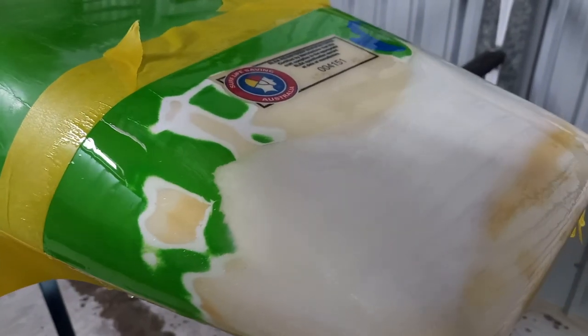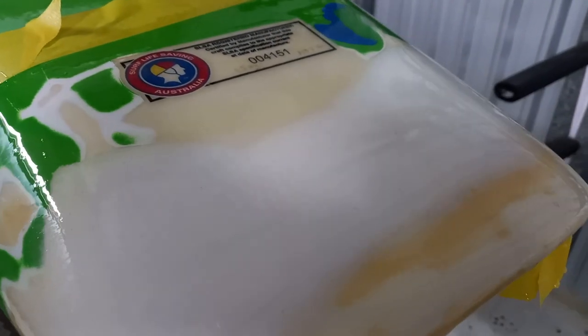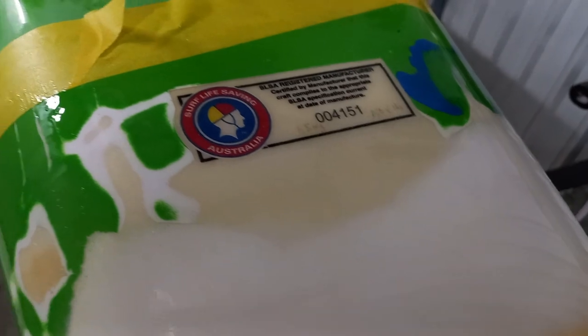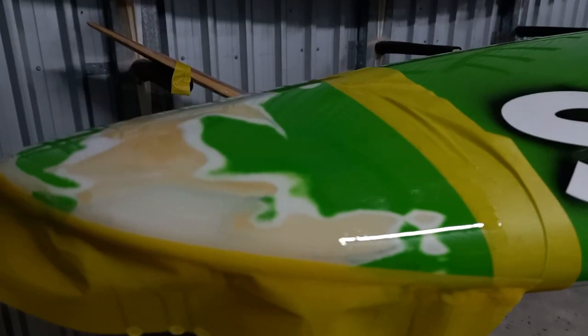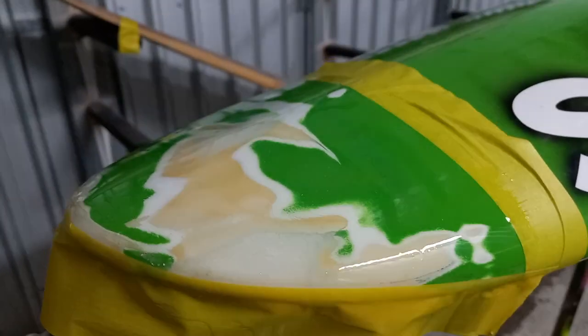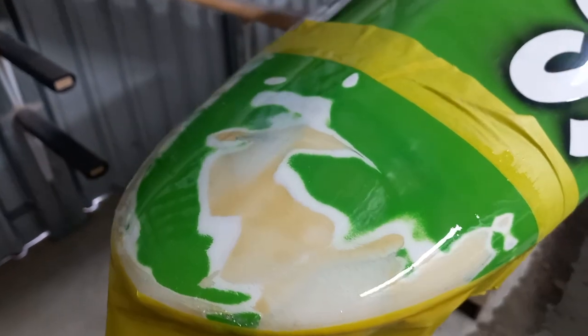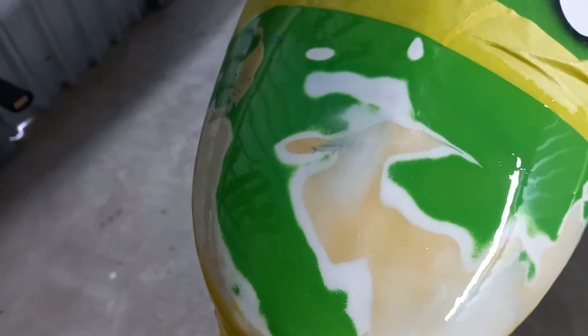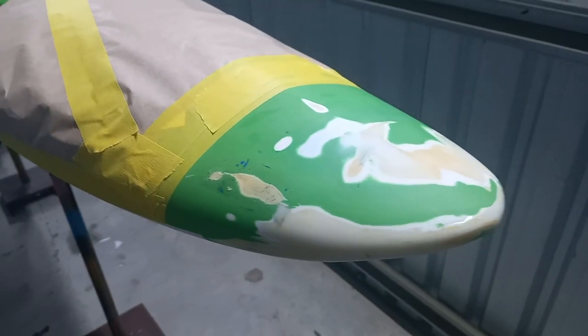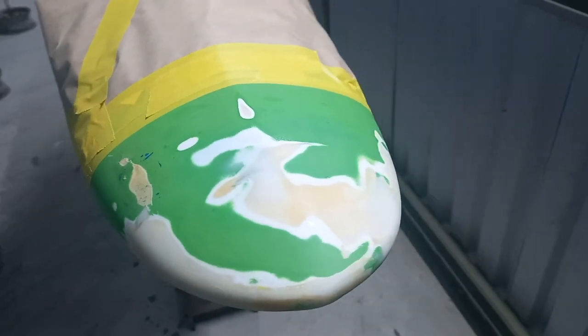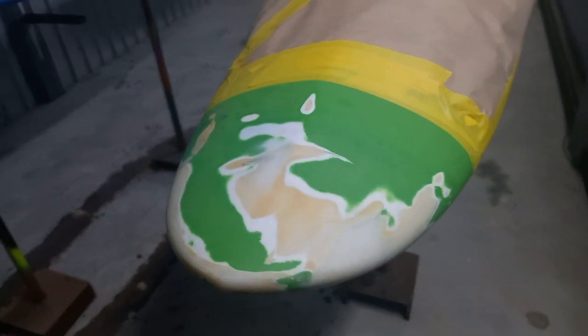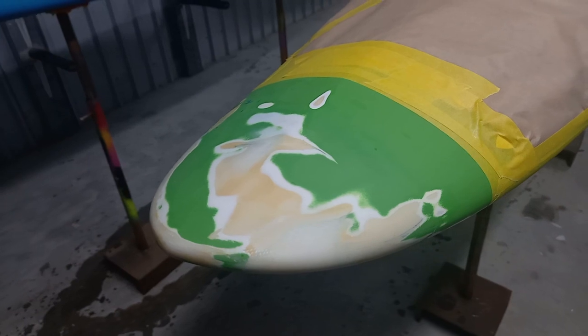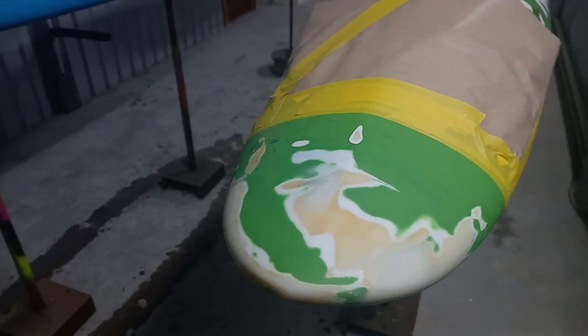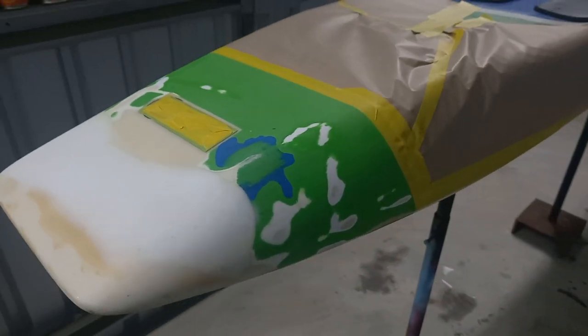Once our hot coat is cured, we're going to sand with 120, 240, 320 dry on the orbital, and then 320, 480, and 600 wet. And we're going to sand further than we need to apply our paint, because we want to put our paint down, put our clear down over the paint, but we don't want to be putting our clear right up to the edge of where we've sanded. So sand further than you need.